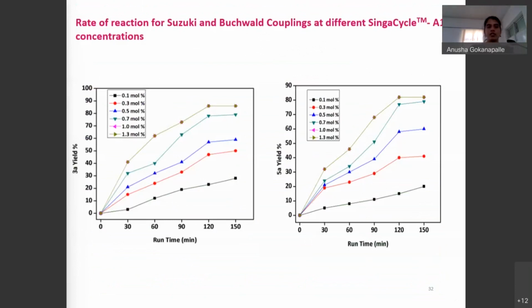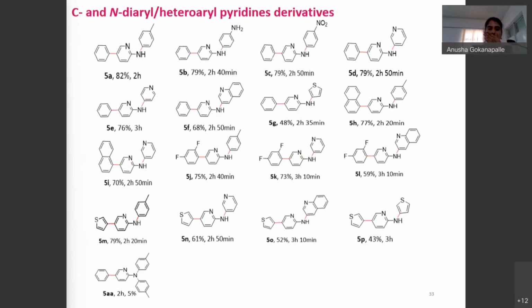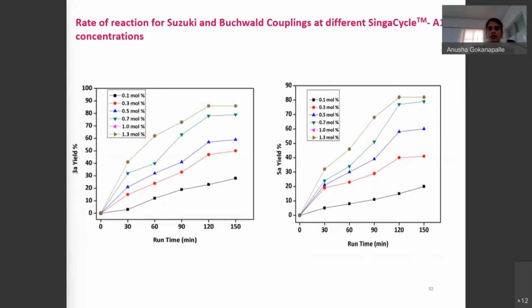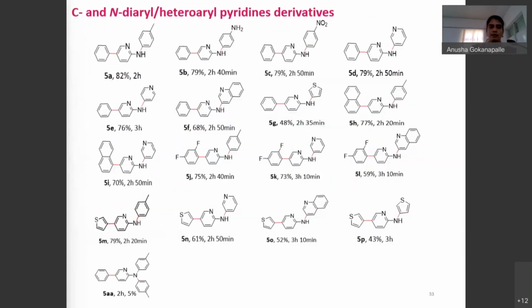Next, scope of reaction for Suzuki coupling reaction. We have tested the efficiency of the catalyst with different catalyst loadings: 0.1, 0.3, 0.5, 0.7, and 1.0. Among all these catalyst loadings, 1.0 mole percent is sufficient for the formation of product. When we increase the mole percentage from 1 to 1.3, there was no improvement in product formation.